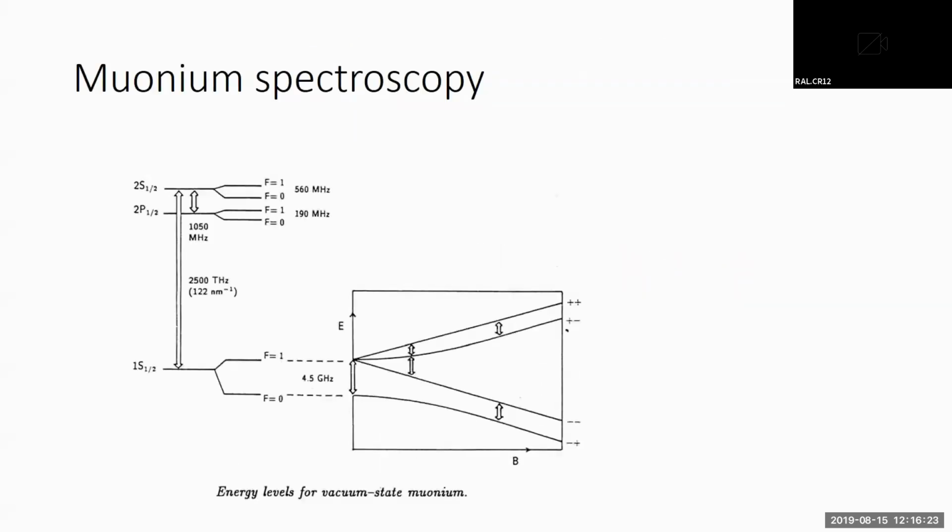Similarly, they then wanted to try to do muon spectroscopy on the materials by applying a magnetic field. If you've got muonium, you can split it into two energy levels, the triplet and singlet states, and then apply a field. These levels vary slightly, and you can measure, for example, the field here. You've got a triplet of signals here, and at a large field, you get two signals here. So you expect to see typically two frequencies from muonium in a high magnetic field, transverse field.